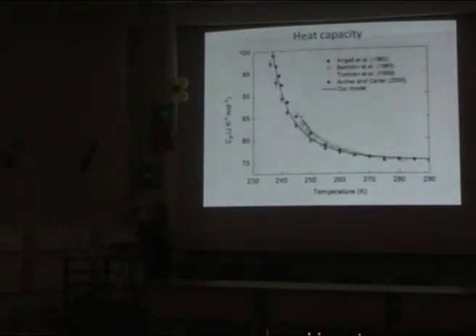This is a derivative of the density, the so-called expansivity. You see the expansivity looks divergent at the critical point very strongly, according to the theory. Data are limited, but at least they describe it. Next slide. This is heat capacity. Heat capacity is more controversial because there are many data sets, and they're not exactly the same. So we need to have a compromise, which is very close to the classical data of Angell in the 80s. But the red line is just the prediction of the two-state thermodynamics. Next slide, please.